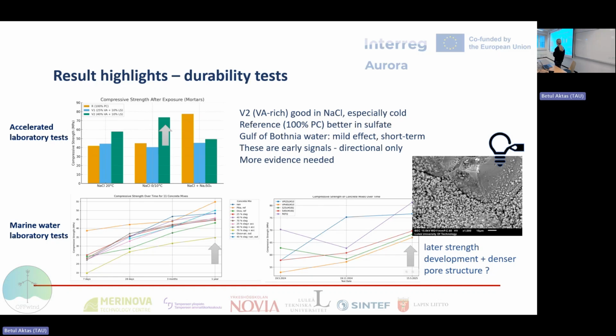If we look at the highlights from the laboratory tests, where we tested the different low carbon mixes with volcanic ashes and slag together with Novia, we can see that actually the low carbon concrete in some cases presented better behavior than the reference mix, which gives possibilities to study this further.